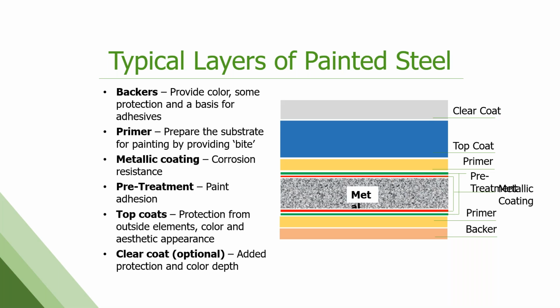That provides corrosion resistance. After that, we have a pre-treatment that's applied, which helps with adhesion and again, corrosion protection long-term. After that, there's almost always a primer applied to both sides of the strip. Primer does a couple things. It helps provide bite and adhesion for the top coat that's going to go on. It also adds in another layer of corrosion protection.